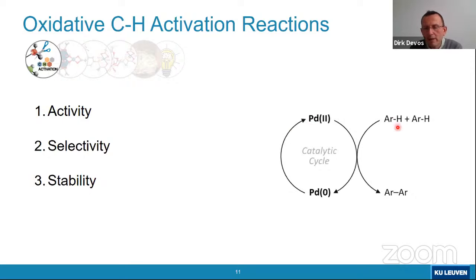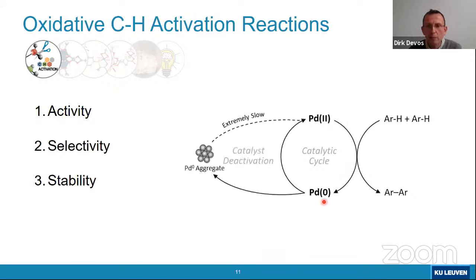In what sense? Well, essentially, the formation of a biaryl can be considered as a dehydrogenative reaction, meaning that you oxidize the two arenes to form a biaryl molecule, but that also means that the electrons are left to the palladium, which in this act is then reduced from palladium 2 to palladium 0 in the quite simplified version. Of course, in the palladium 0 state, the palladium will be very susceptible to make palladium aggregates, and reoxidizing palladium from an aggregate to palladium 2 is going to be very difficult. And in fact, if you have too much palladium aggregation, that comes down to catalyst deactivation.